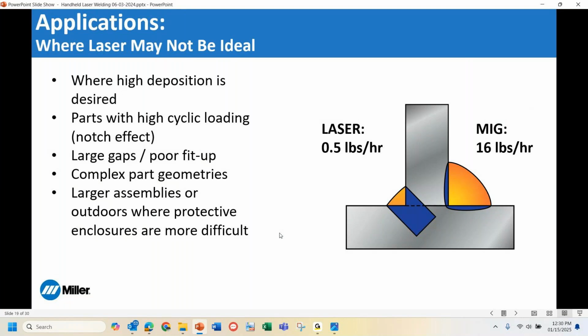And then the other thing to consider is if it's an outdoor environment, like constructing a building, for example, because we have to construct barriers or protect those that are not involved with the welding from that potential scattered or emitted laser energy. It may become more complex to ensure the safety of those individuals. And so for the most part, the handheld laser welding up until this point has been mostly implemented in an indoor manufacturing or fabrication type environment where we can have static containment with barriers and walls. It becomes, like I said, much more difficult once we start moving outdoors.